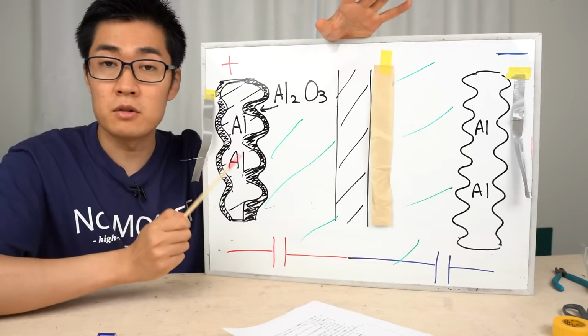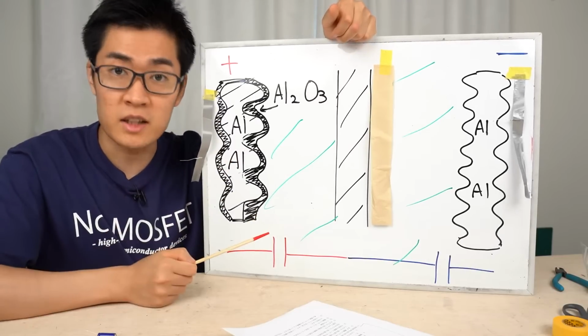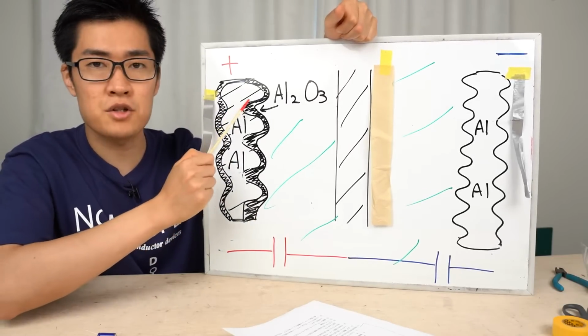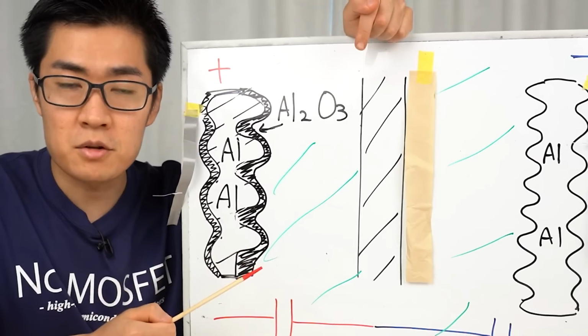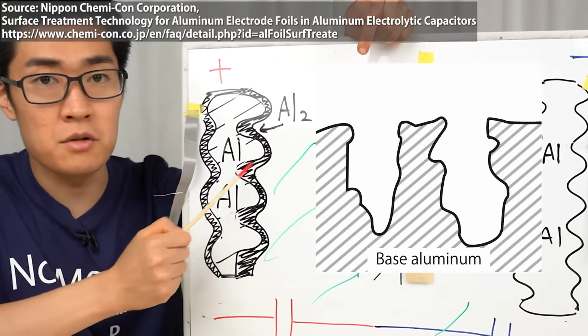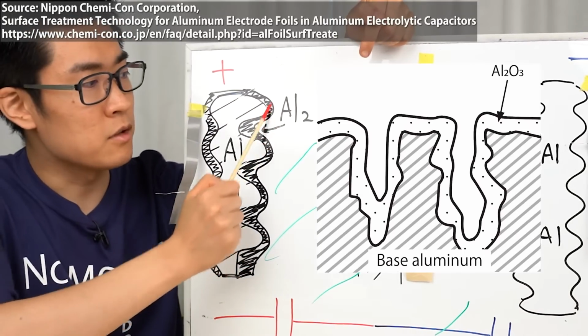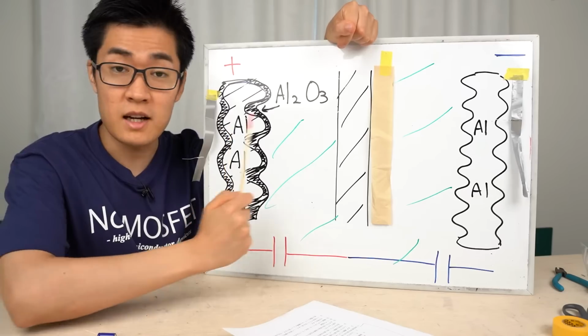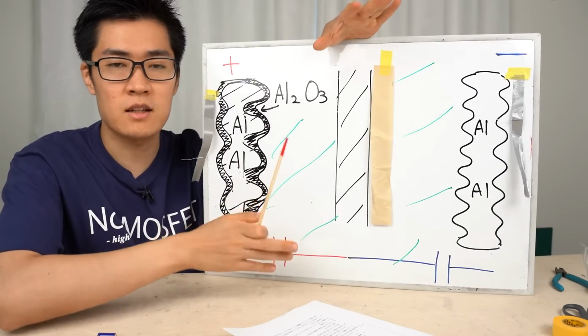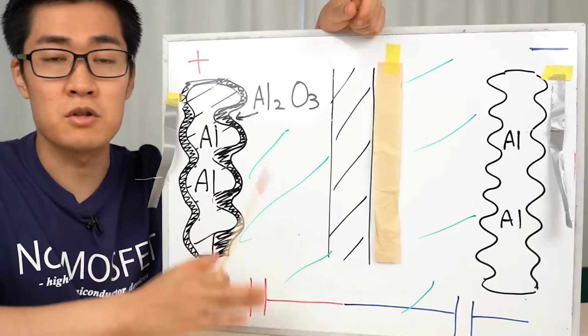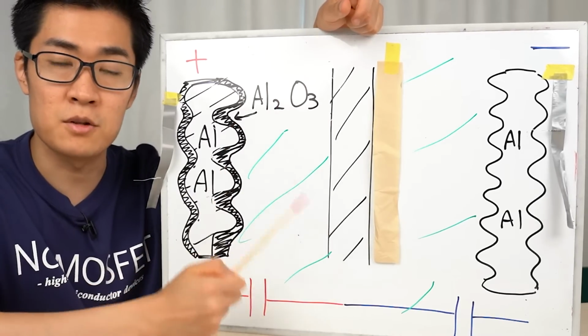it clearly. After that, the anode foil goes through the forming process to raise the withstand voltage of the electrolytic capacitor. In the process, a dielectric layer is formed on the surface of the aluminum foil. In this case, the dielectric is aluminum oxide. Then the treated aluminum foil and separator are wound together. Once they are impregnated with electrolyte, an aluminum electrolytic capacitor element is complete.